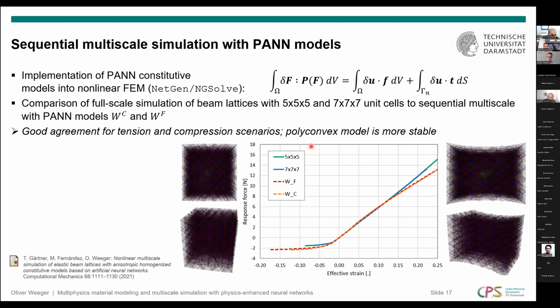So remember, we fitted the model to the behavior of such a lattice microstructure. Now we simulate such lattices using a full-scale simulation where everything is discretized using beam elements here in some sort of tension and compression cases. And we compare this against the multiscale simulation where we use the material models with physics-enhanced neural networks. And you see here that there's a good agreement of the full-scale and the multiscale simulation.